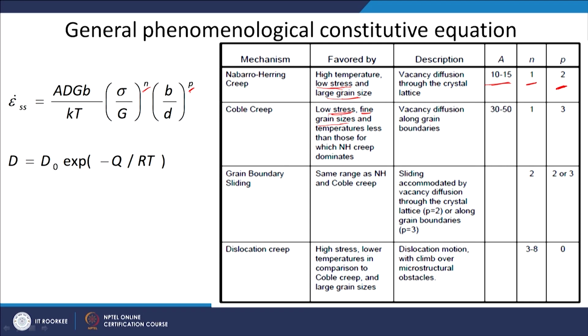Vacancy diffusion through the grain boundary, A is in the 30 to 50 range. Of course, the stress exponent is again 1 here, whereas the grain size exponent is 3. Then grain boundary sliding can be in the same range as Nabarro-Herring or Coble creep, sliding accommodated by vacancy diffusion through the crystal. So again p is equal to 2 or 3, depending upon whether the diffusion is taking place through the crystal lattice or along the grain boundary, but n in this case is 2.